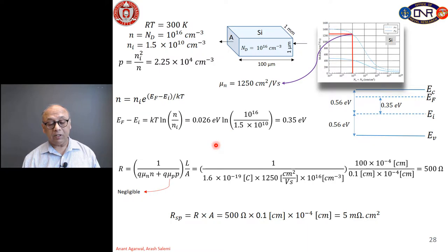Now, to calculate the resistance, we know that the resistivity due to the drift phenomena is 1 over (q mu_n n plus q mu_p p), and we can look up electron mobilities and hole mobilities from this chart I've shown you. We can see that electron mobility is about 1250 centimeters square per volt second for a doping of 10 to the 16 per centimeter cube. This term we can neglect because the number of holes is at least 12 orders of magnitude smaller than the electrons.